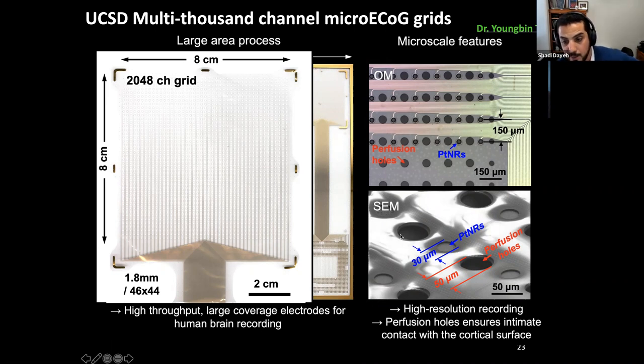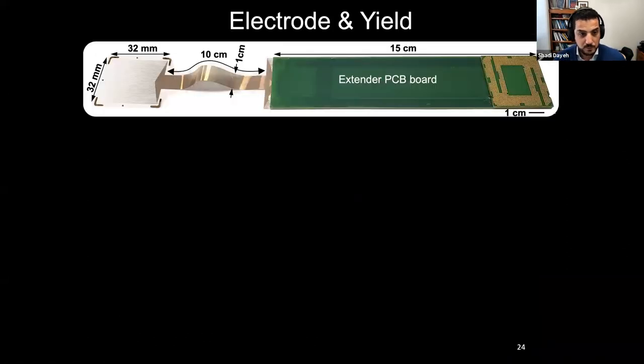And this is an SEM image that again illustrates the same, where the platinum nanorods are recessed below the parylene surface. And we have the holes across the whole parylene C layer.